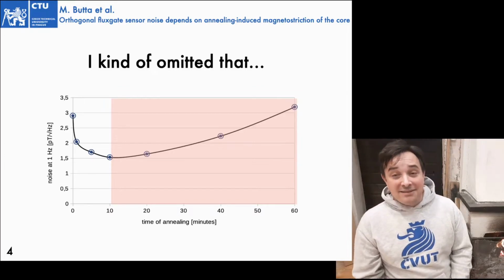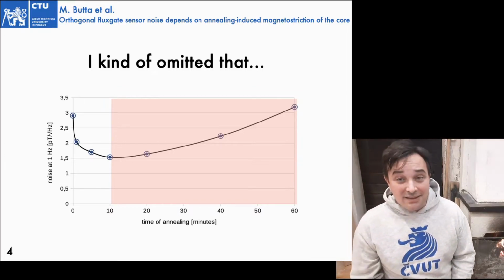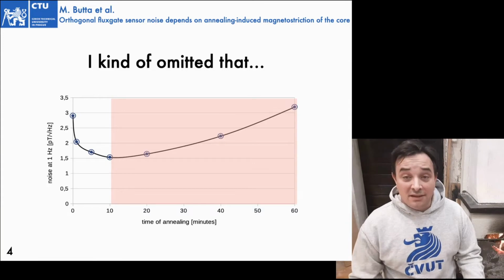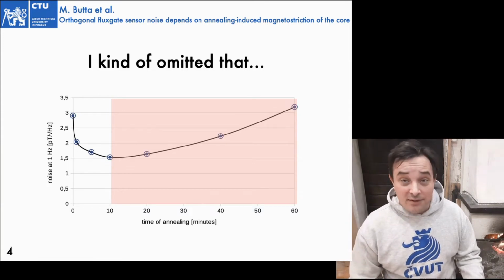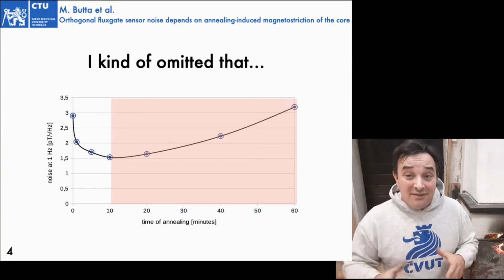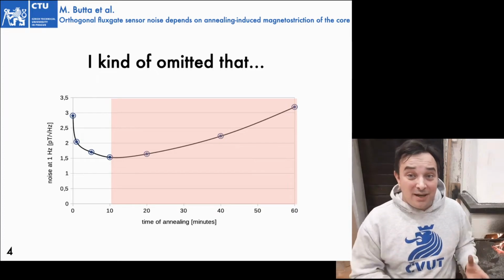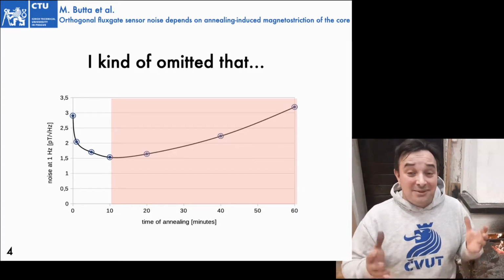As a matter of fact, if you anneal for a longer time, the noise rises back. For instance, if you anneal the wire for 60 minutes, you end up with a noise which is even larger than the noise that you have with as-cast wire. So it really makes no sense to anneal the wire for 60 minutes.